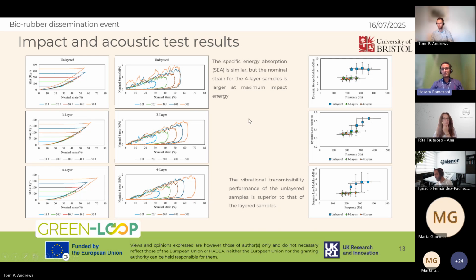And finally, the acoustic properties are completely different because here the unlayered sample has the better performance in terms of dynamic storage modulus, dynamic loss factor, and as a result, a higher dynamic loss modulus. This shows that depending on the design of the material and on the type of the coating that we are using, we can use these recycled rubbers and coated rubbers in various applications. This concludes my presentation.